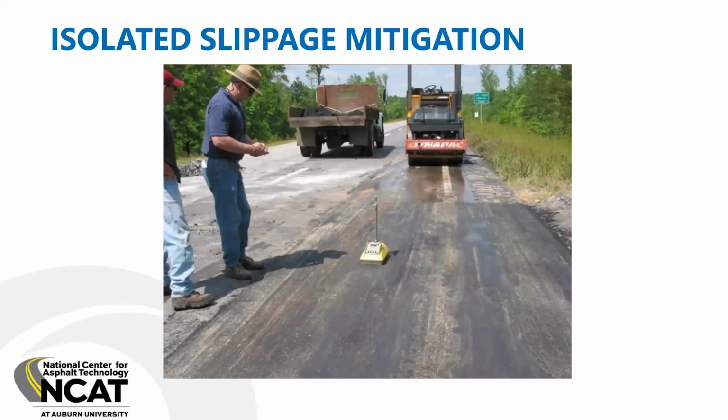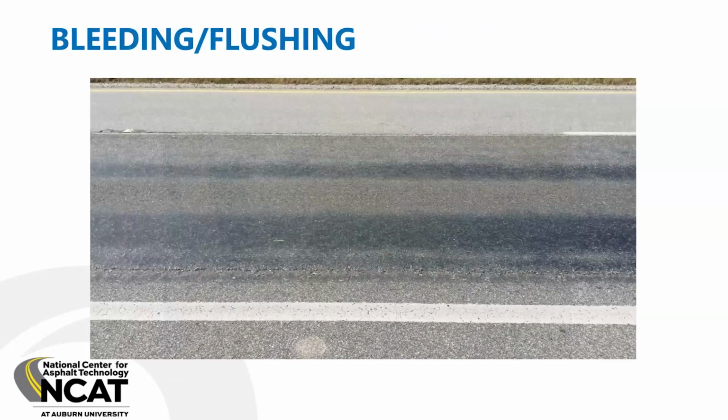We actually used the exact same mix that was in that surface layer, and we compacted it to the density of the original surface. And all of that was so that Dave Timm could continue his structural research without having the results confounded. And the outcome of that experiment was actually very positive. Very good repair.